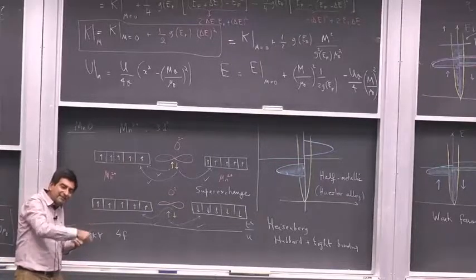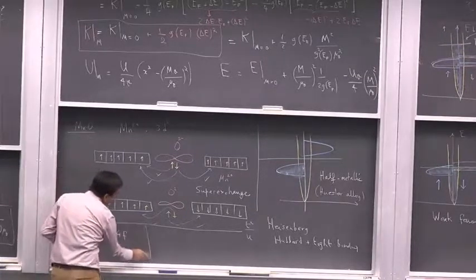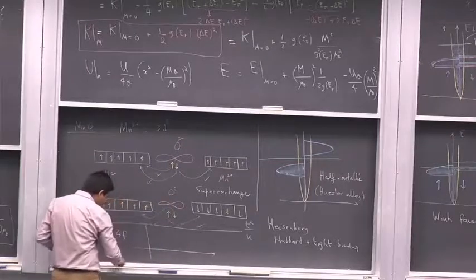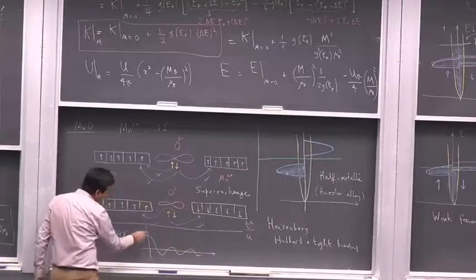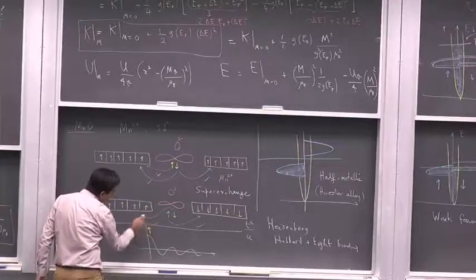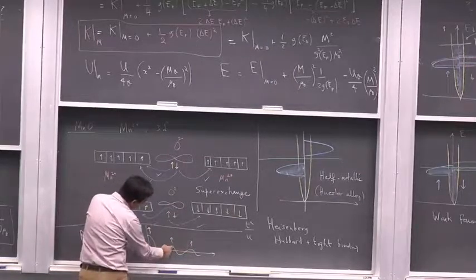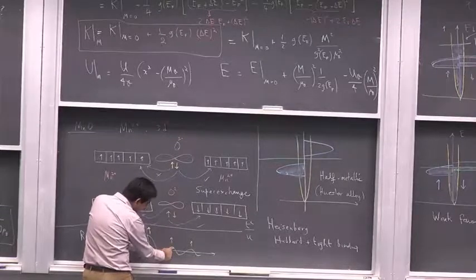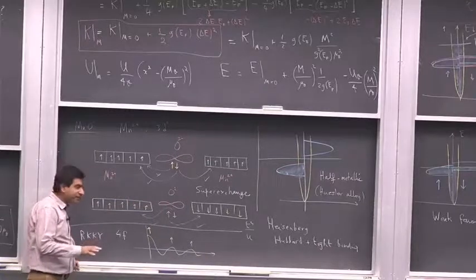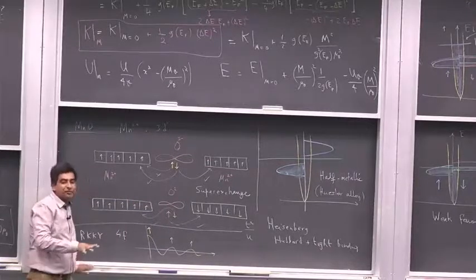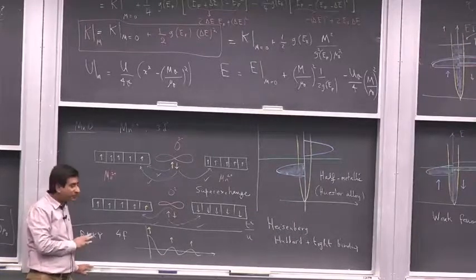The ion polarizes the electrons, and then the wave function of the electron takes an oscillatory character. At certain locations you have spins of one kind, at all the crests you have spins of one kind. So if this is the interaction between two magnetic ions, with this distance, then those magnetic ions would like to order ferromagnetically. This kind of interaction is mediated by the conduction electrons, and it's called an indirect exchange interaction. The RKKY interaction is one example of this, and we don't have time to go into it.